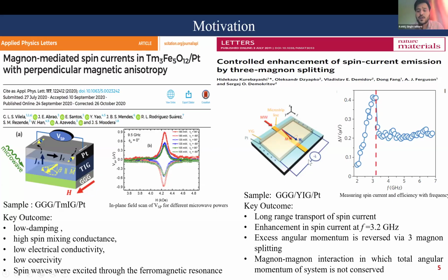Parallel to this, other literature reported work on YIG, the well-explored material, in the low-frequency region, giving a rise in the spin pumping potential because of the splitting of one magnon wave into two with the lattice interaction. So it would be interesting to find out if the magnon can also help us in the production of an increased spin pumping potential at some interface.